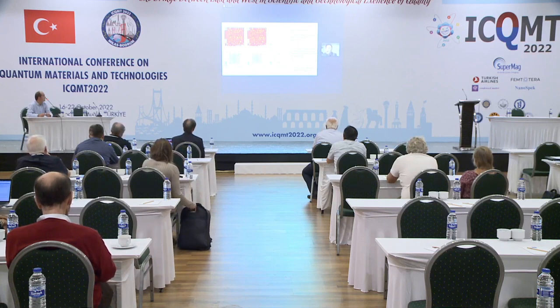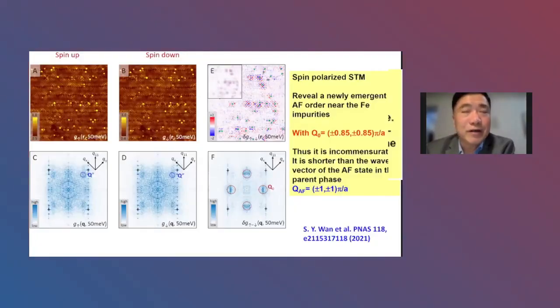Oh, actually, in China, I think several groups can reproduce this monolayer thin film. Tsinghua University and also other universities, like Shanghai Jiao Tong University, can produce this monolayer iron selenium film, and the quality looks quite nice. That's possible, but in my group, we have not tried that direction yet. Certainly in iron selenium thin film, people try to find the Majorana mode on the vortex core. It seems on the intercalated iron selenium film people find such a zero mode, but in iron selenium monolayer film, it does not exist. So it could be interesting.